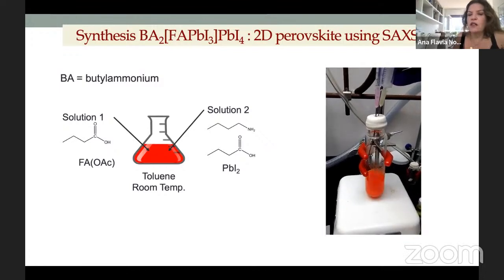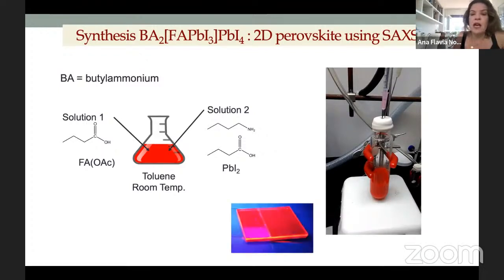It's very quick. And then you have the formation of these very nice 2D perovskites in micro size, okay? And also we can deposit these films on a substrate, and depending on the number of layers, this is for n equal to 2, where you have two 2D layers. In fact, it's a very nice luminescent material.